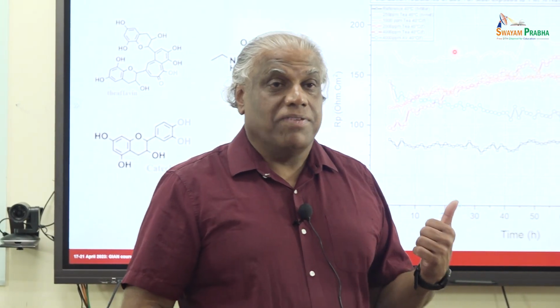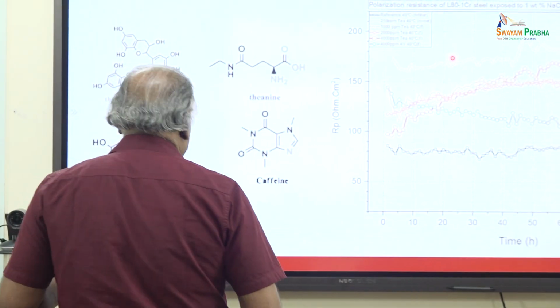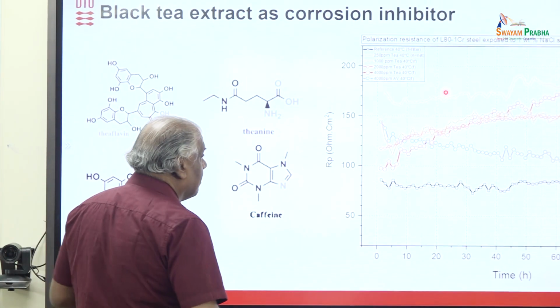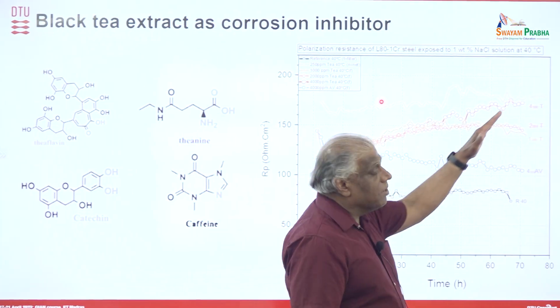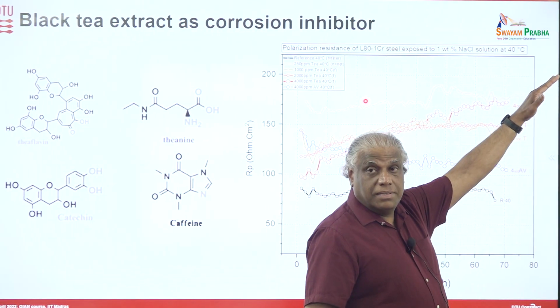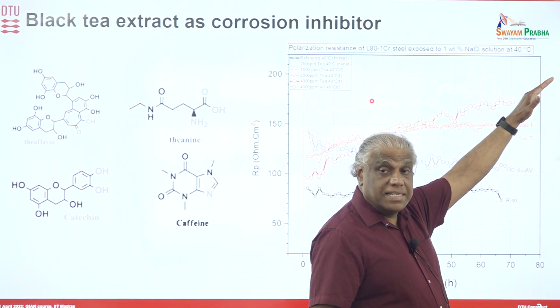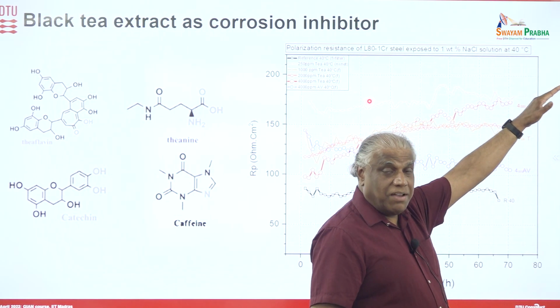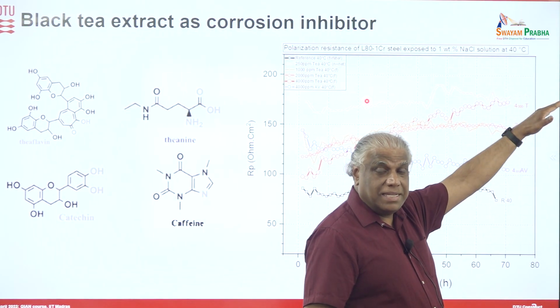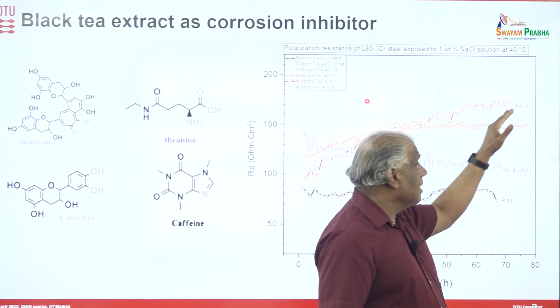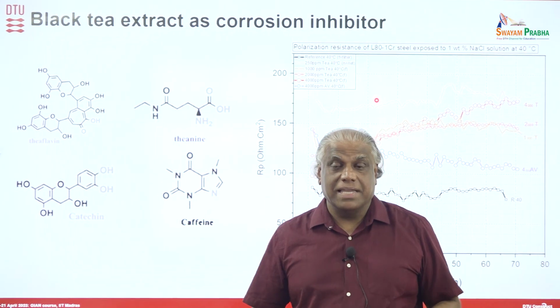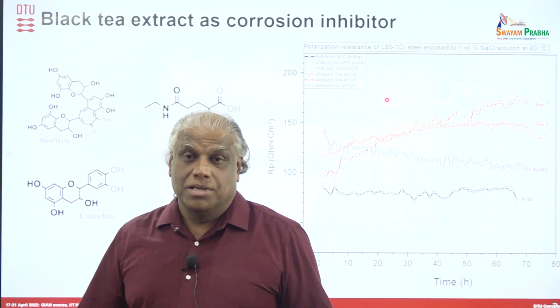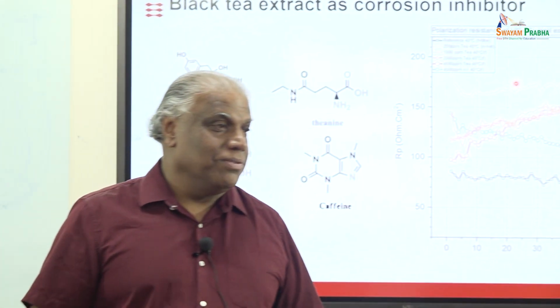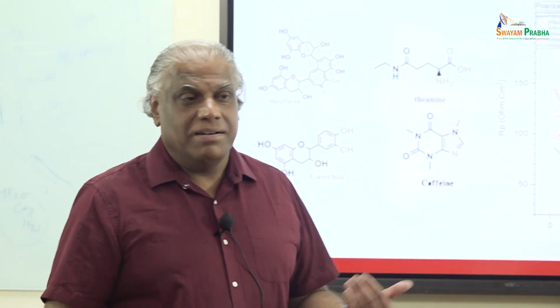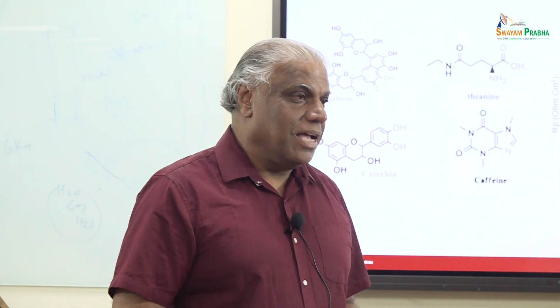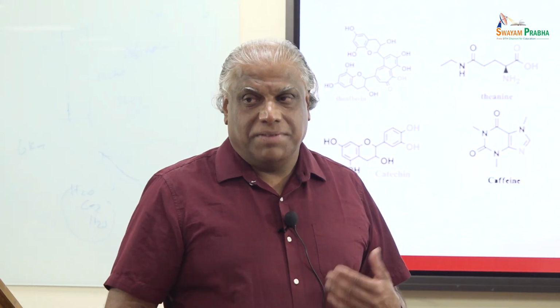But one good thing we found with this black tea is that the inhibition keeps going up. Even after we ran the experiment for 30 days, it is maintaining that level, and it has increased more than this, but it remains at that level. It's never coming down. So from the inhibition efficiency point of view, it is working very well compared to the aloe vera extract, and that way it's better.